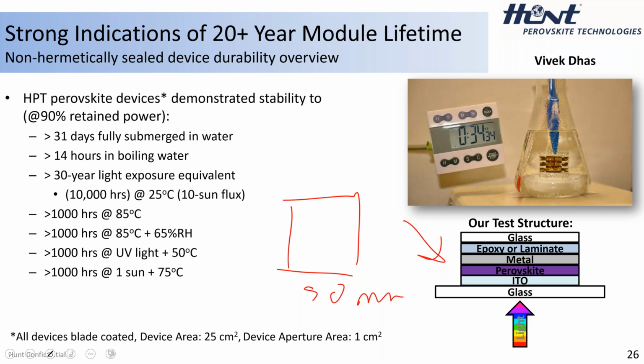But more importantly, things that are more aligned with the kind of IEC type test, but IEC plus, because we don't have a fully packaged or sealed device, is that we have 1,000 hours at 85C, and the cells are able to maintain more than 90% of their total power output. Further, we can take 85C, combine it with 65% relative humidity, and also maintain more than 90% of their power over 1,000 hours. Further, light plus heat, so UV light plus heat, and then one sunlight plus heat. And we have these devices quite stable and quite durable, maintaining 90% of their power under all those conditions.